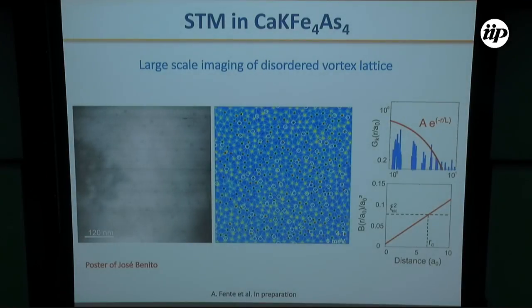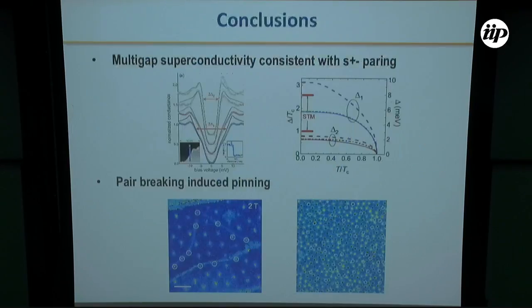So when we calculate this positional correlation function, we find that it decays exponentially, indicating that we have a short-range hexagonal order in the lattice. We have also calculated the relative displacement correlator, obtaining a correlation distance of a few lattice spacings for this material. A more detailed characterization of the disorder has been made by Jose Benito and can be seen in his poster.